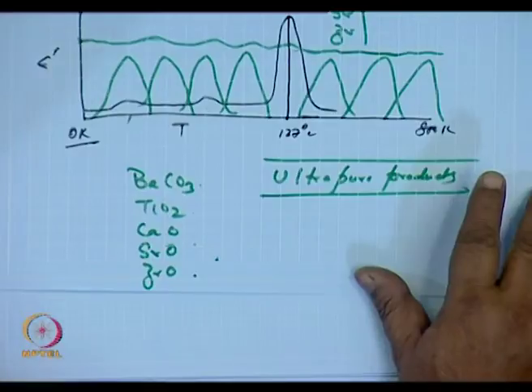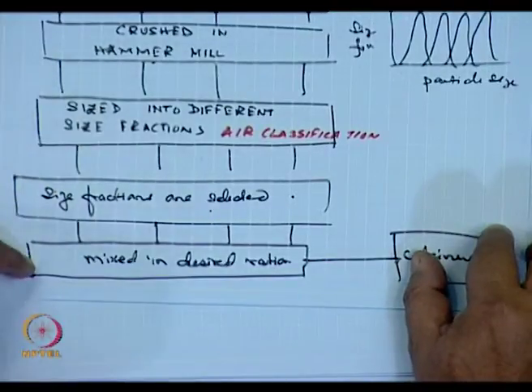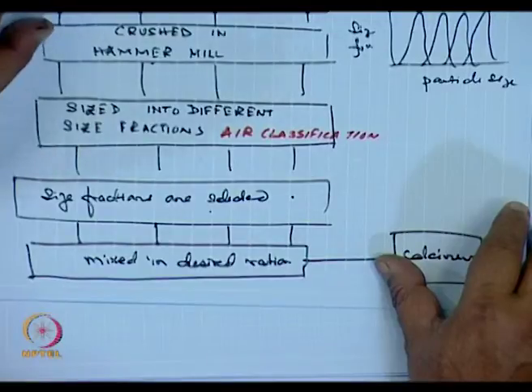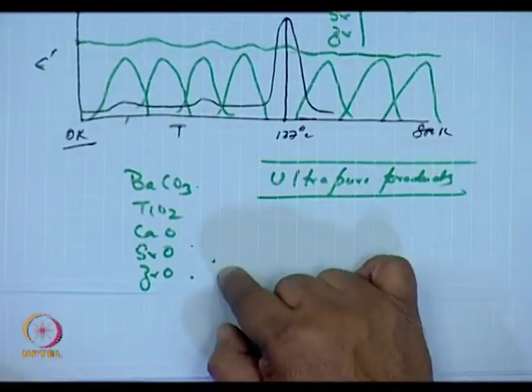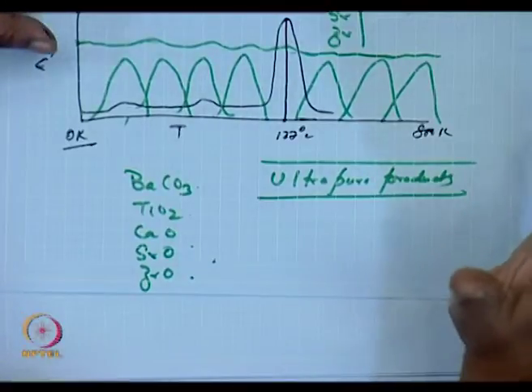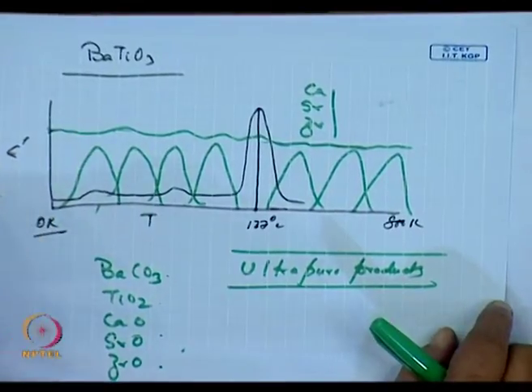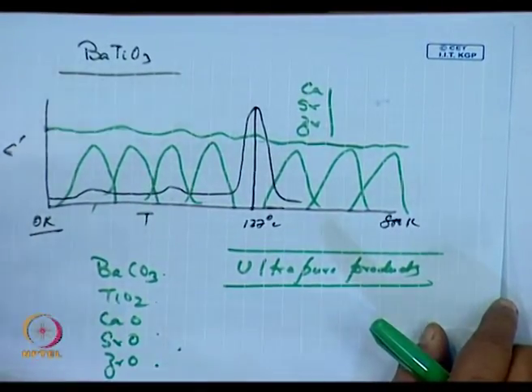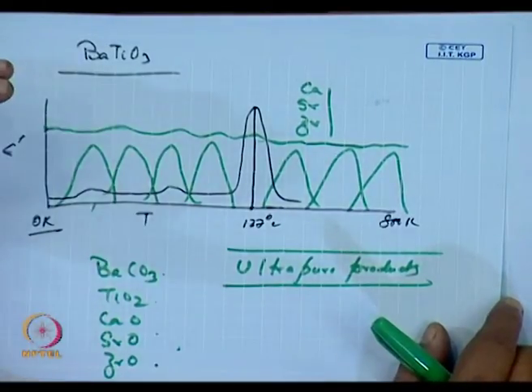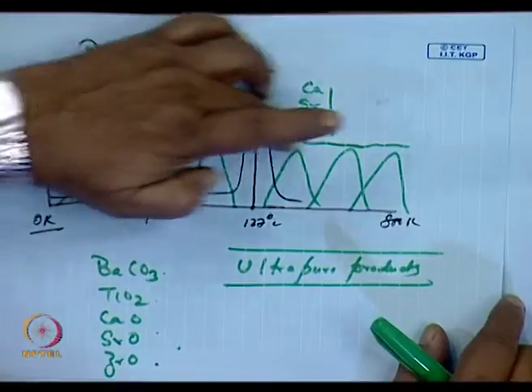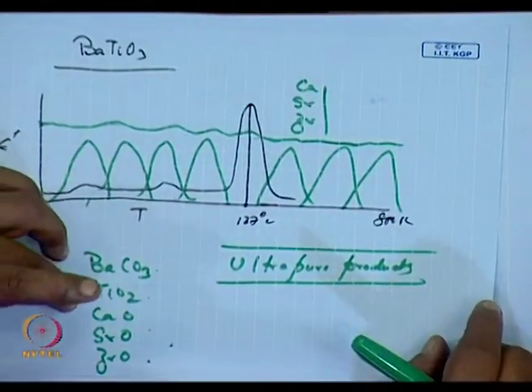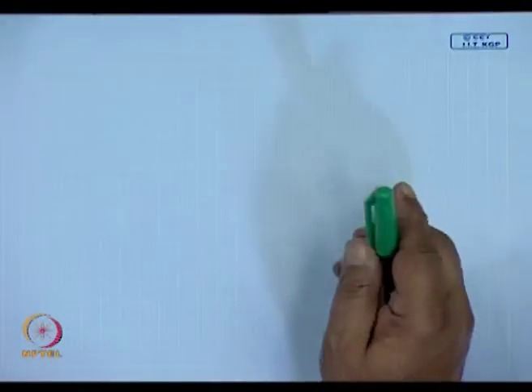If we had tried to use any of this process for synthesizing the powder over here, we would have a useless powder. So, here, for this sort of a capacitor which I am talking of, which has got a very high dielectric constant, which is used in space, which has got a constant dielectric constant over a wide range of temperature, for mixing so many products, the only viable process that we have is a ball mill.